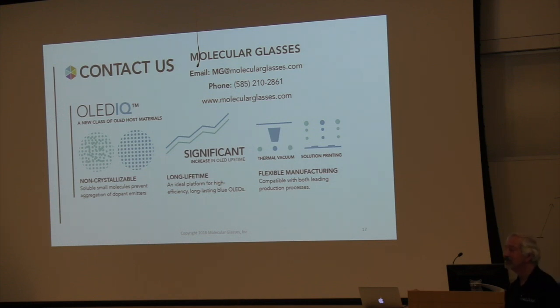Please. So what are the electron and the hole conductivity of your material? I can't hear you, I'm sorry. Electron or hole conductivity of your material? Yeah, about 10 to minus 4 centimeters squared per volt second. 10 to minus 4. So it's about the same as the vacuum deposited materials, but very slow compared to what physicists are used to.